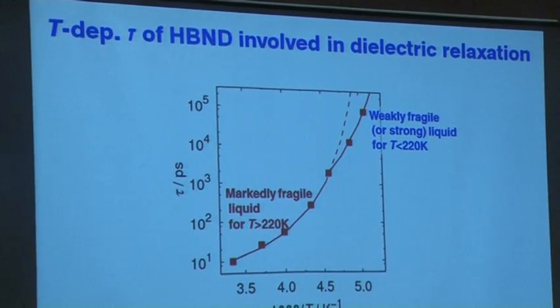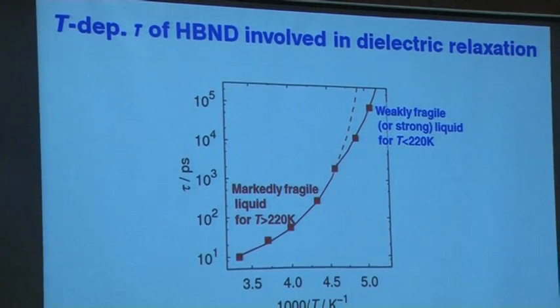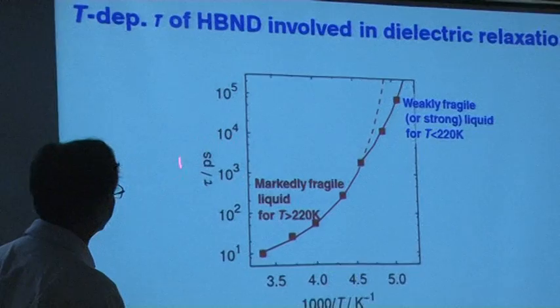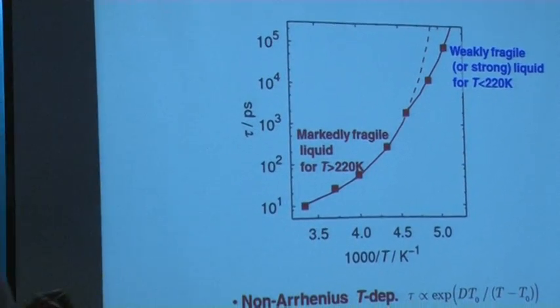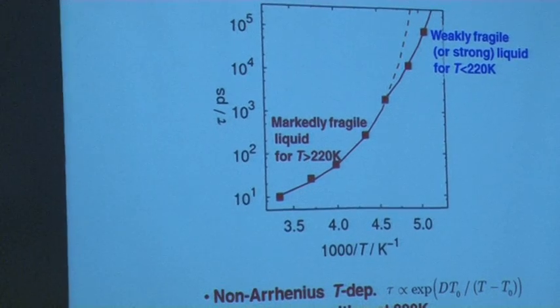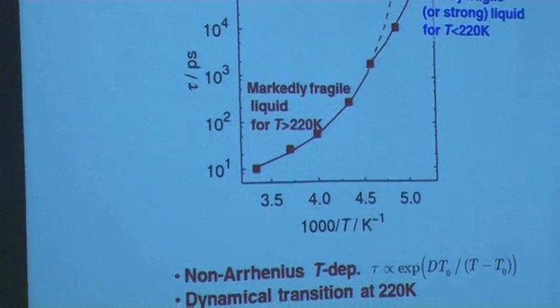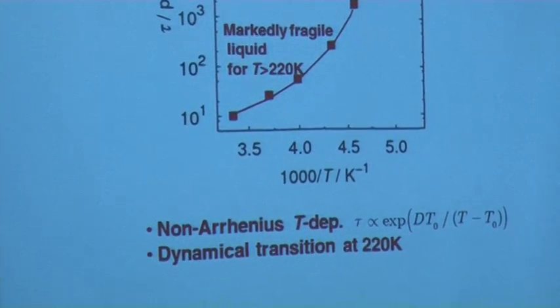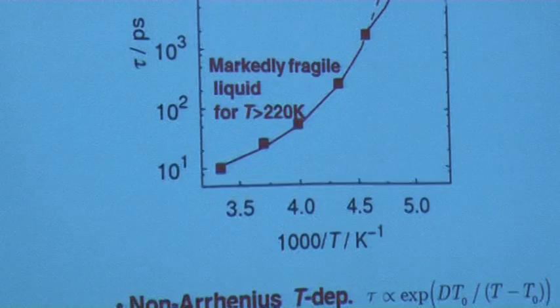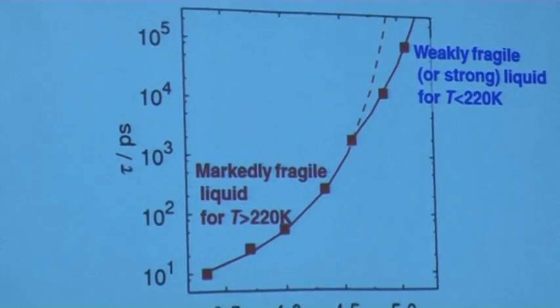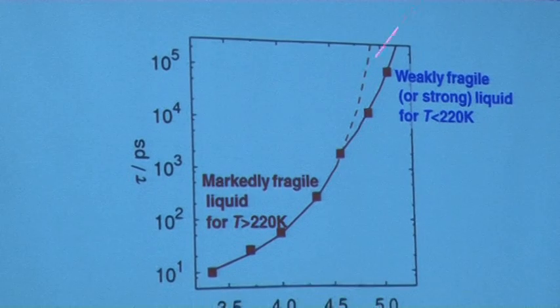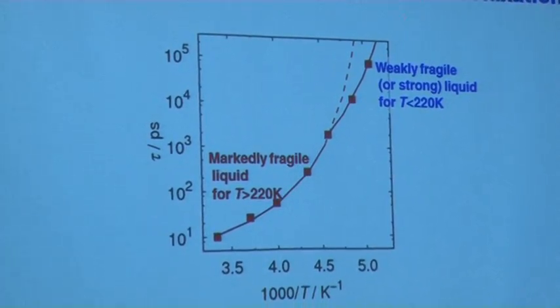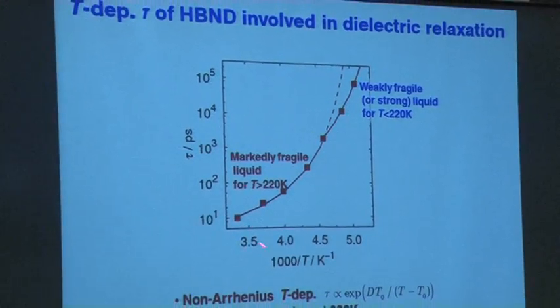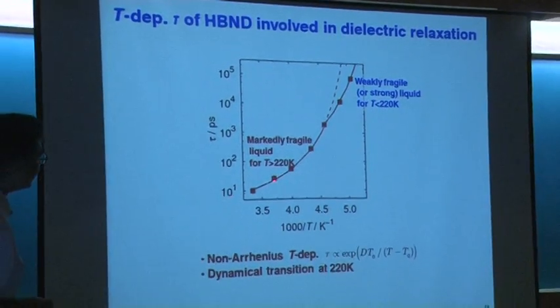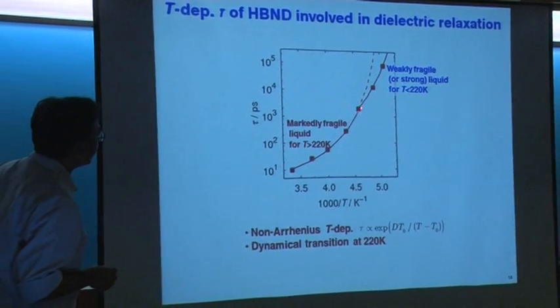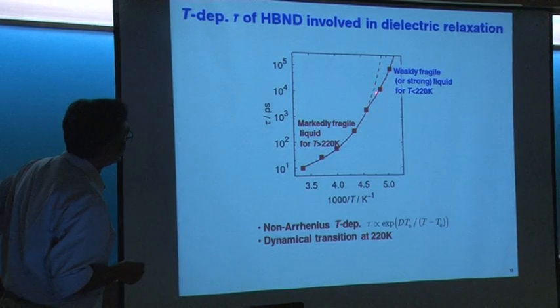Again coming back, now I just want to spend a little bit more time on something which I have not talked about before, that is the temperature dependence of the relaxation time. I can get the relaxation time by dielectric relaxation, by frequency dependent susceptibility, by hydrogen bond dynamics, I can get it in n number of different ways. Or the structural relaxation time from dynamic scattering, the dynamic structure factor, and all of them show similar behavior, almost universality. From high temperature, 300 Kelvin, this is 1 over temperature, down to 220, you have this branch, and then the liquid transforms to a different branch at 220 Kelvin.